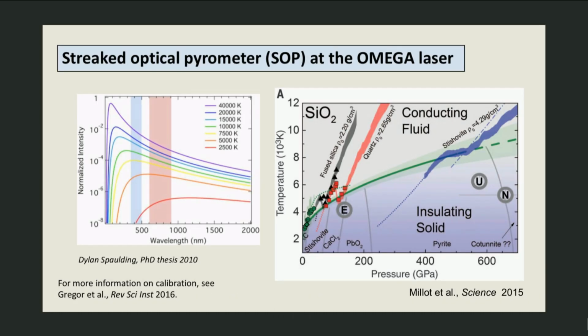Another technique is looking at the emitted photons, and so this is using pyrometry. The better coverage that we have of the entire wavelength spectrum, the better constraint we have on temperature. But at different places, we use what we can, where we look at just the emitted counts of photons, and then compare it to a calibrant to determine what the temperature is emitted from our sample. And we can take advantage of this in experiments of decaying shock, where we send in an unsupported shock through a sample. As an unsupported shock travels through the sample, the emission out of the front of the shock, a skin depth from the shock front, is actually just the black body, gray body emission. And so we've been successfully using that to measure temperature.